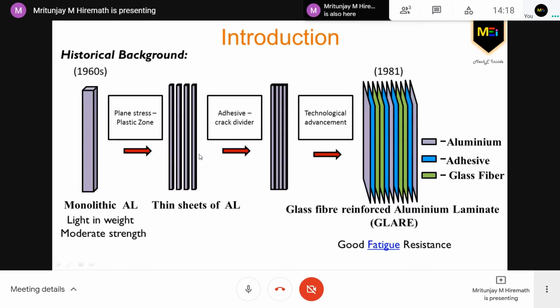Coming to historical development, in the early 1960s, aerospace structures were solely developed from monolithic aluminum because of its light weight and moderate strength. But there was a problem in the fatigue resistance. It could not bear the fatigue whenever it was exposed to such a harsh environment. Therefore, an idea of 2 sheets of aluminum was developed, wherein from the concept of plane stress, whenever there is a crack present in the aluminum sheet, the plastic zone at the crack tip reduces the crack propagation rate. And if these aluminum sheets are joined by adhesive that acts as a crack divider, it makes the crack propagation rate lower by 3 to 4 times.